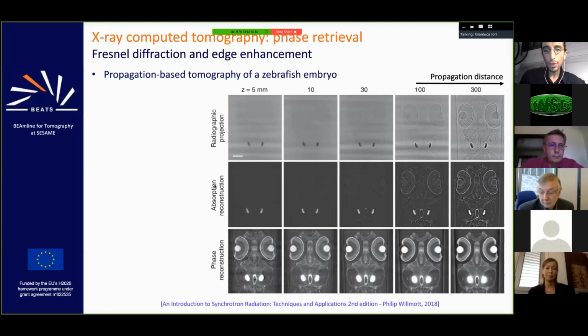The features that we see, I was saying, the first row is radiographic projection, the second row is normal absorption-based tomographic reconstruction, the third row is phase contrast tomography. So the features that we see in all these images are calcium earstones, which the fish is using for balance. And actually, this is dense, and therefore is the feature that we see in all the pictures. But the rest is all soft tissues.